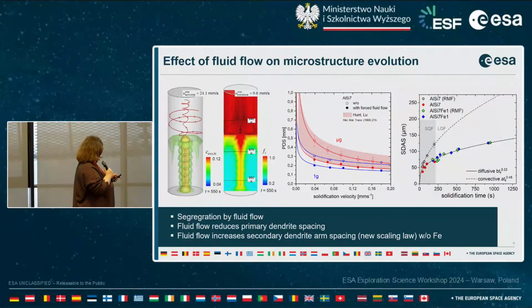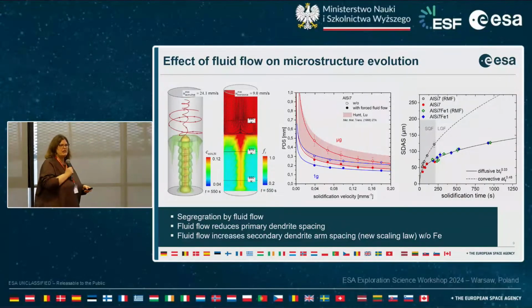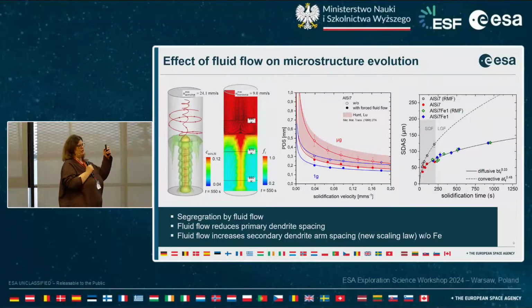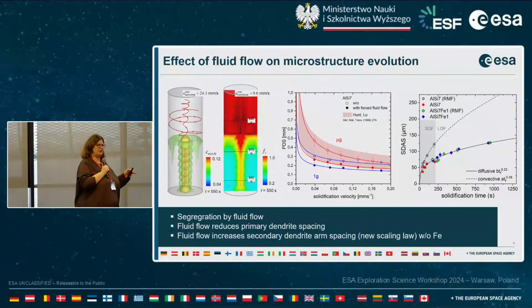The other parameter, which characterizes the dendritic microstructure on longitudinal sections, is the so-called secondary dendrite arm spacing. This means the side arm spacing of your Christmas tree. And it is well known that these side arms, because you have not a fixed melting point, your dendrite is always in a solid-liquid transition. It stays a while in contact with the liquid. It evolves. And this is a so-called coarsening process. You can think about it like the smaller dendrite side arms will be eaten by the bigger ones, depending on the curvature of the dendrite tips.